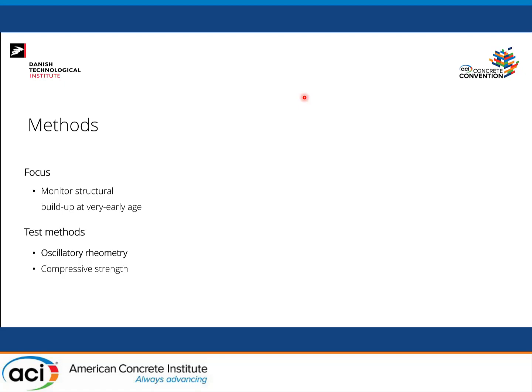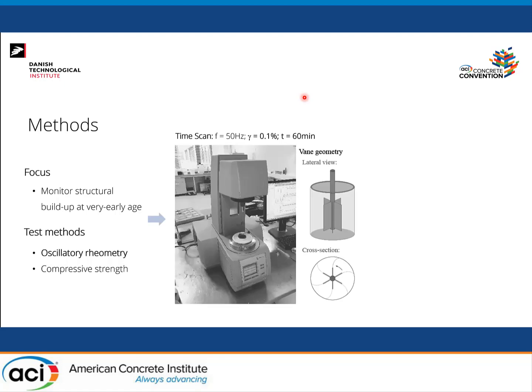But I highlighted the oscillatory rheometry aspect here, because we're doing a time scan, so we are basically mapping G prime and phase angle over time using a vane geometry. We have a relatively stiff mix from the start, as you see in some of the printing videos, and we fixed the strain at 0.1% because we identified, prior to doing all these tests, that the linear viscoelastic regime of the material would be up to 0.2 or 0.3%, in a different publication.